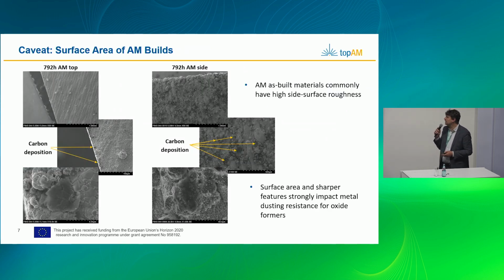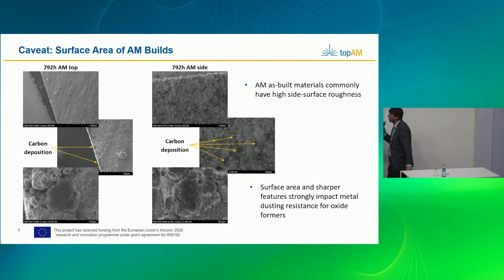The problem is a little bit that we have those rough surfaces. And when you look in closer via the SEM, what you can see here is that you have some carbon deposition. It's without the pointer, a little bit hard to see. Maybe when you have a ground surface or a flat surface, we don't have those kind of weak spots.